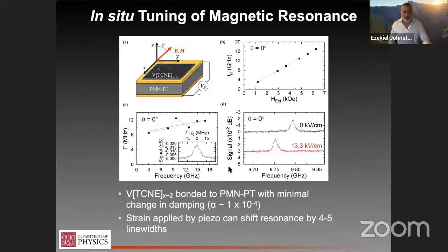And so this was a first hint at an additional degree of freedom here, which is to say strain. So our hypothesis was that the curvature of the substrate is introducing some strain into the system. So we wanted to test that out. The easiest way to do that is just bond a V[TCNE]x film to a piezoelectric. We chose PMN-PT and see what happens.